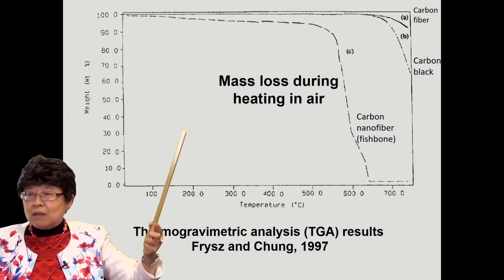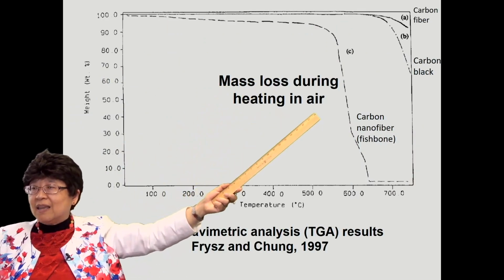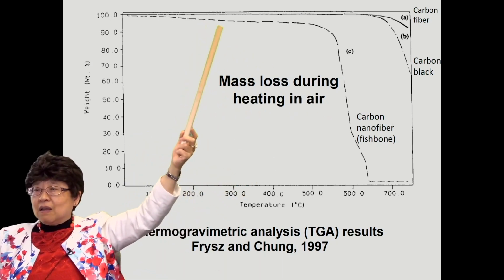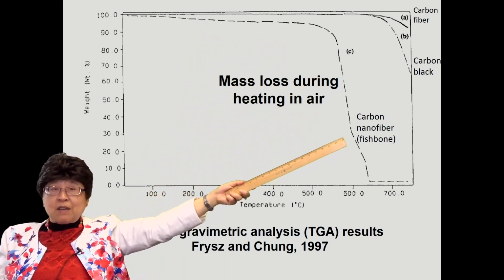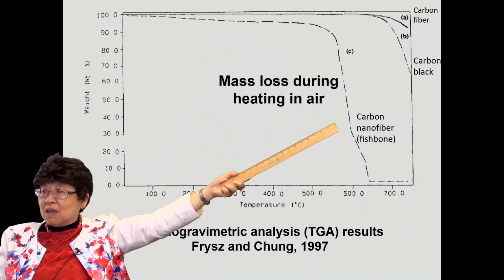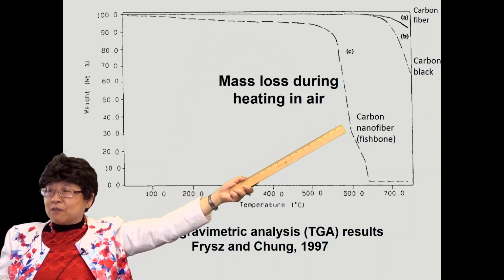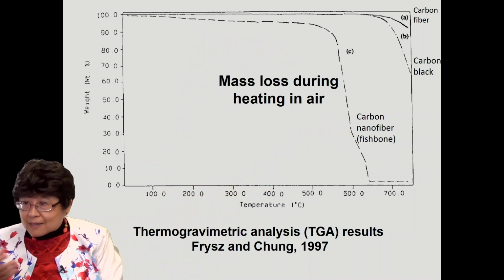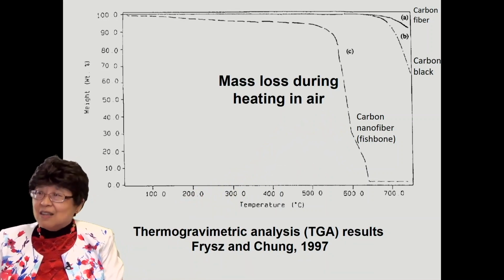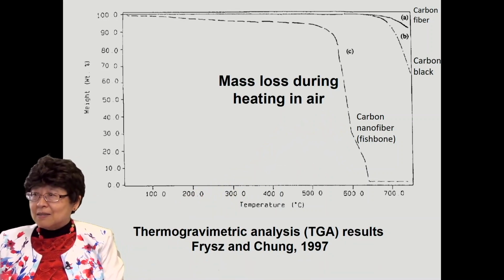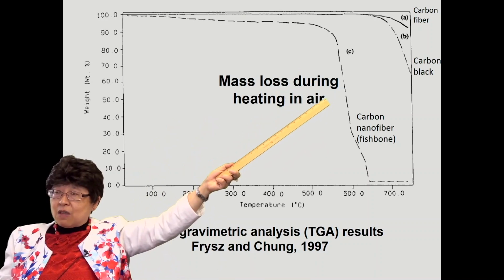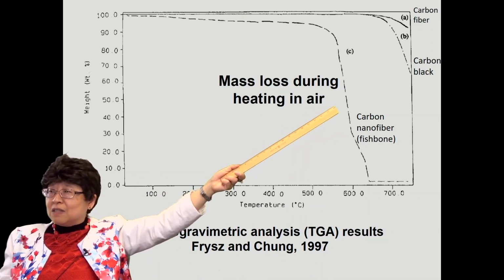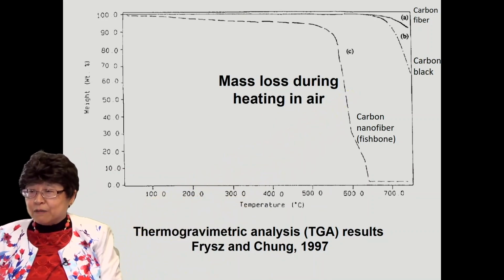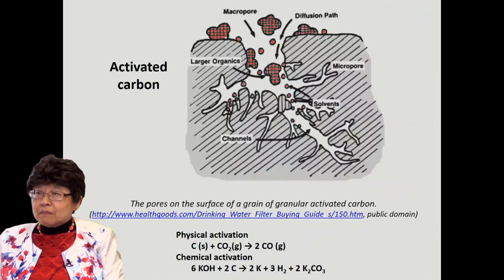And this is the weight loss or mass loss during heating in air. So you have the weight suddenly drops a lot. That's because of the oxidation. And different types of carbon have different tendencies to be oxidized. Some are easier than others to be oxidized. And that's why the onset of the oxidation occurs at different temperatures depending on the type of carbon material.